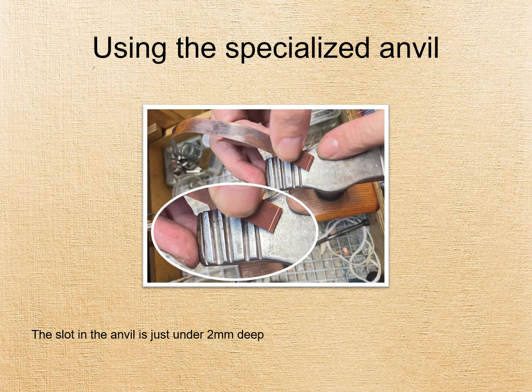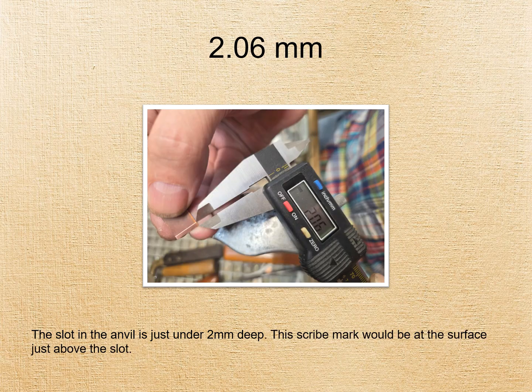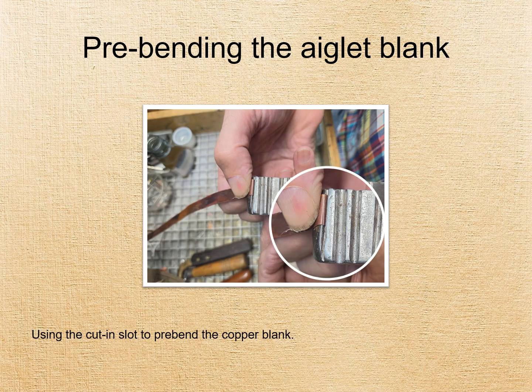The slot at the end of the anvil is just under 2 millimeters deep. You can see here from the scribed mark just how deep it is. You can see how this would help with making a uniform bend for every aglet made. Using the cut-in slot to pre-bend the copper blank is more efficient than trying to bend these with pliers.